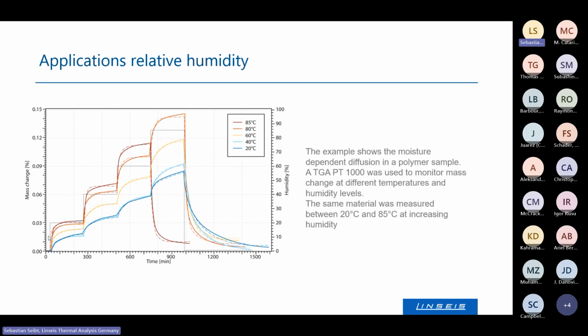So you need a little while until the system gets stable. Then you heat up again, the system gets stable, you heat up again, the system gets stable, and so on. However, what you see is, as the same sample was used at different temperatures.